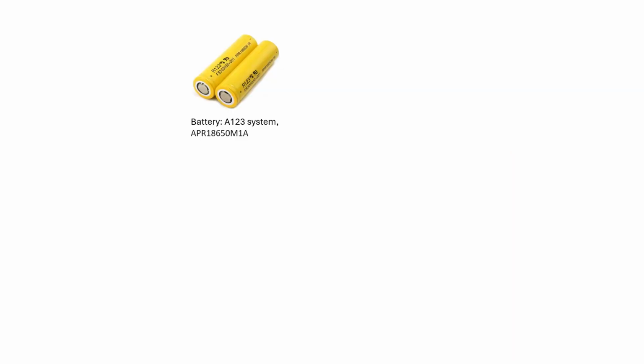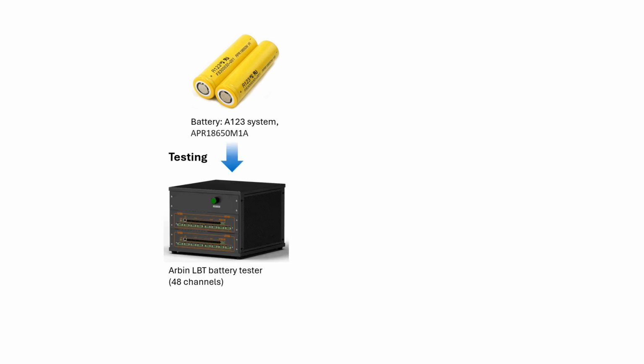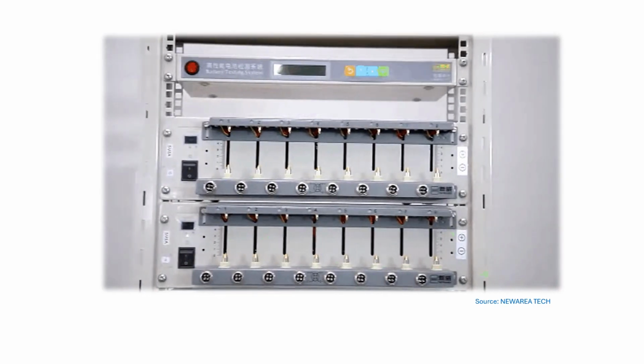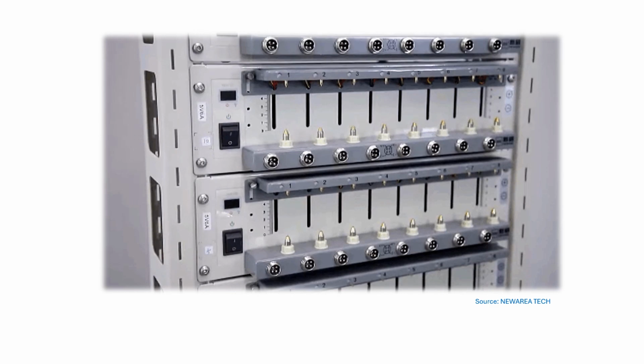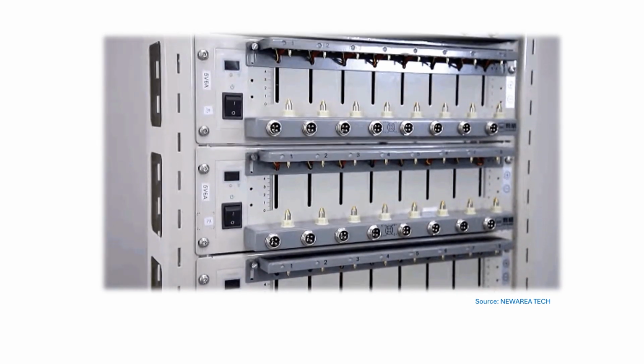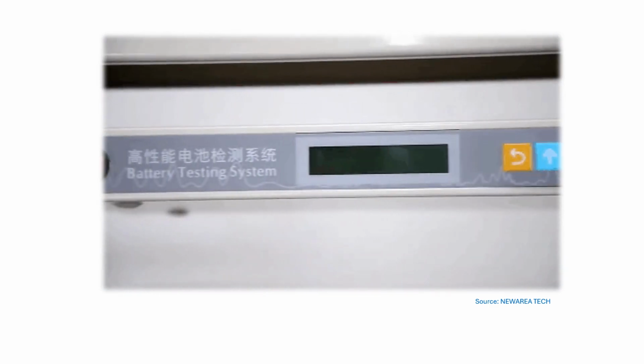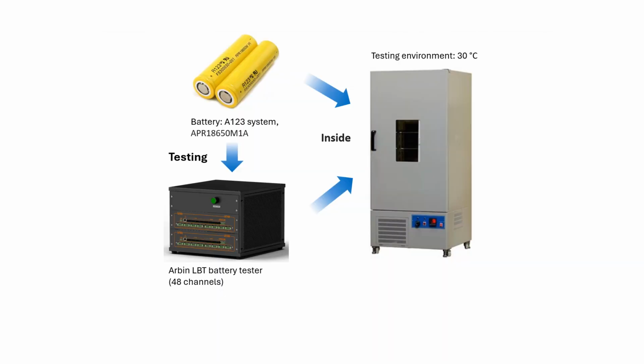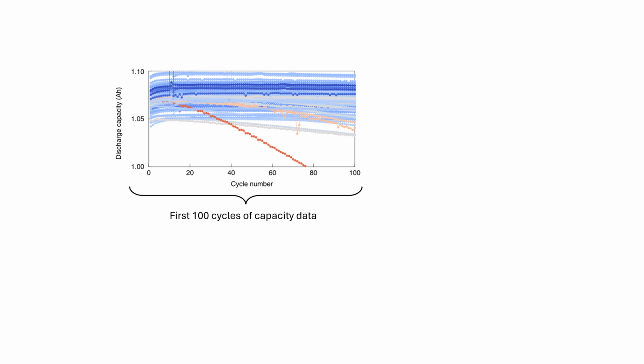The batteries used in this study are from A123 Systems, and testing is conducted using an Arbin LBT battery tester. A battery tester repeatedly charges and discharges the batteries, simulating real-world usage while monitoring key parameters such as capacity, efficiency, and degradation. To maintain consistent testing conditions, the setup is placed in an environmental chamber, keeping the temperature constant at 30 degrees Celsius. With the dataset in hand and using machine learning algorithms, this work demonstrated two key findings.